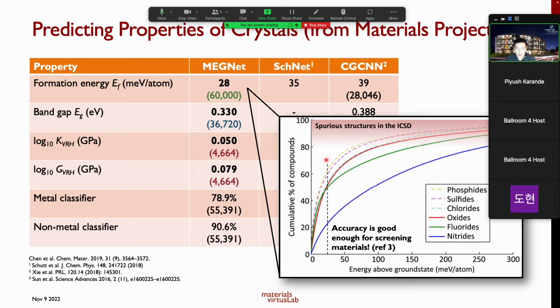And just to give you a sense of whether this 28 meV per atom is enough, there's this work that was done by Wenhao Sun back in 2016, where he looked at basically the energy above the ground state for all the structures in the Inorganic Crystal Structure Database, right? Most of the crystals in the ICSD have actually been synthesized. So if we look at all these structures, we find that about 80 or 90% of those structures fall within this 100 meV per atom threshold above the ground state. So if we can predict the formation energy with an accuracy of about 28 meV per atom, this is already well within that limit. So in other words, we have sufficient accuracy that we can give a good prediction of whether a material is likely to be synthesizable or not. Okay.